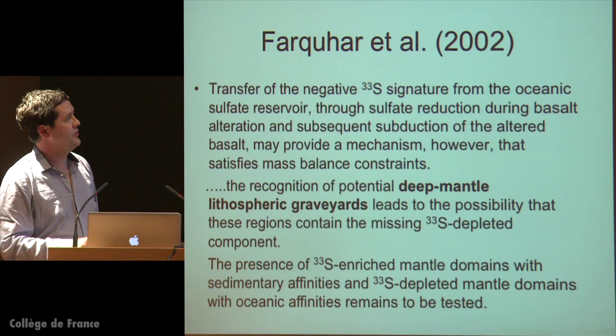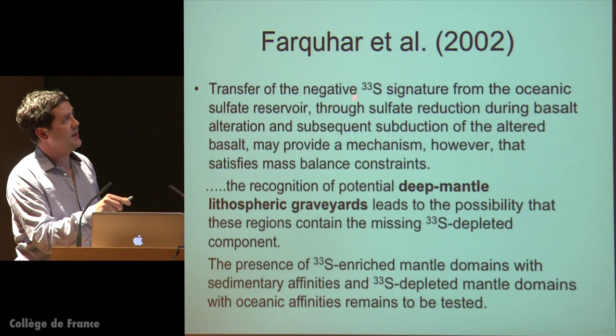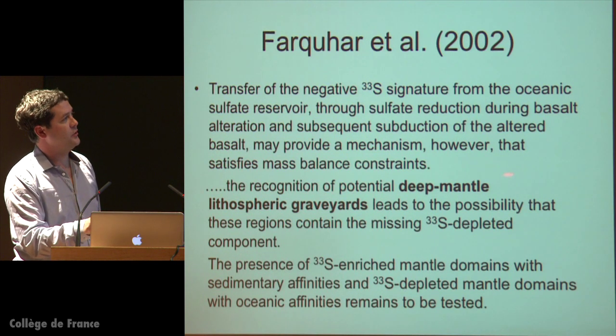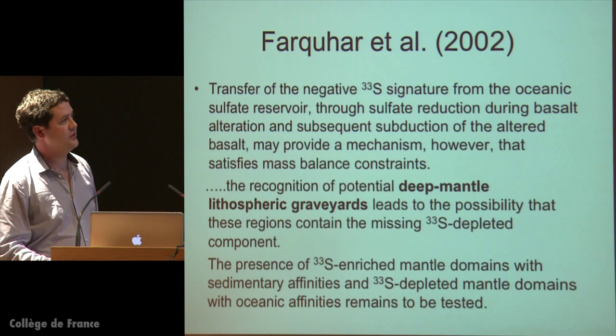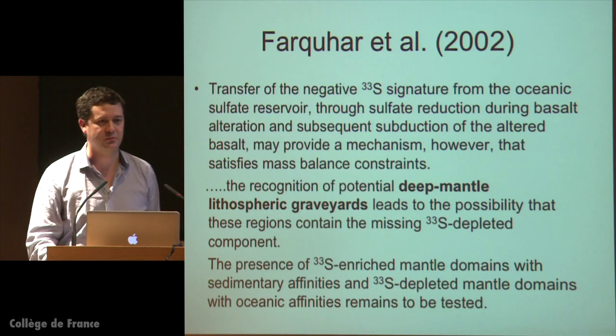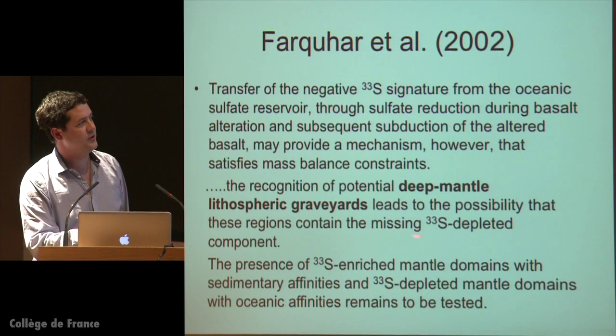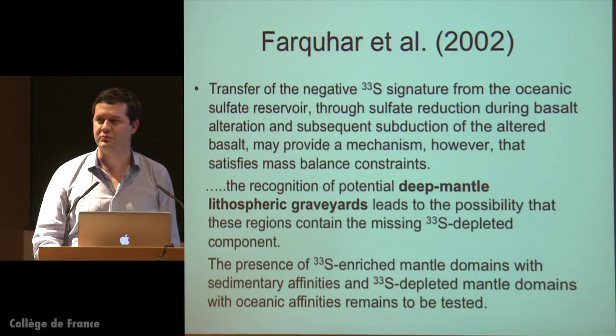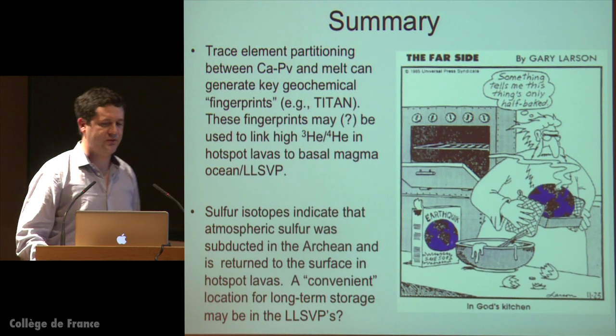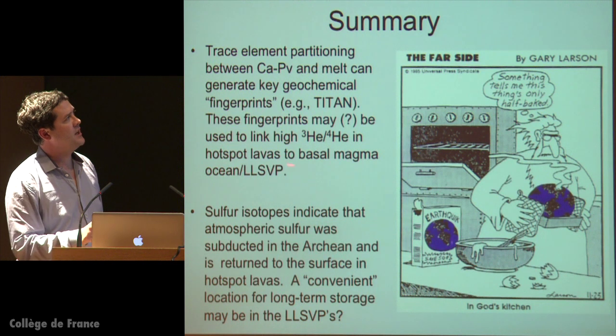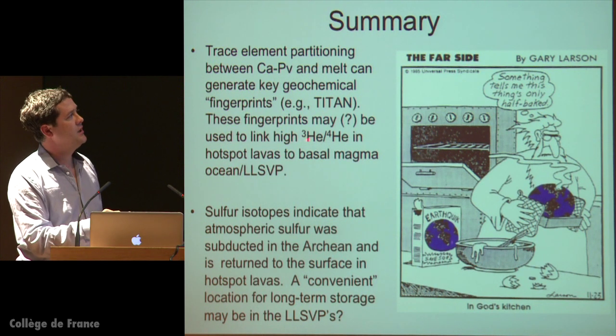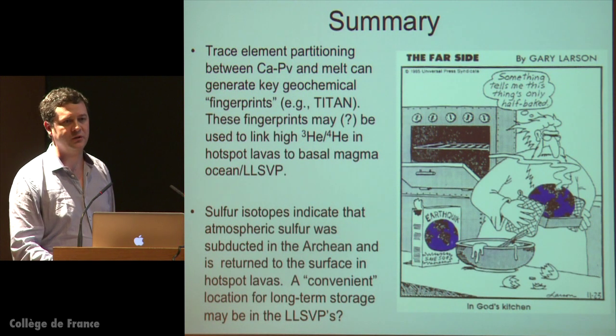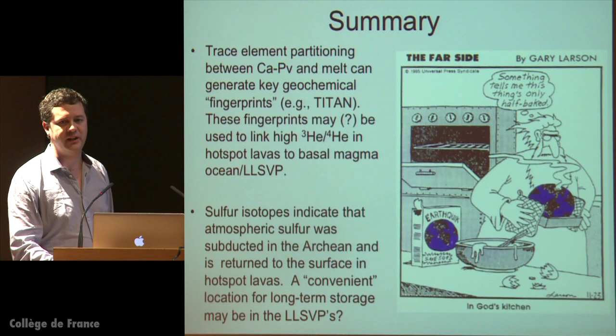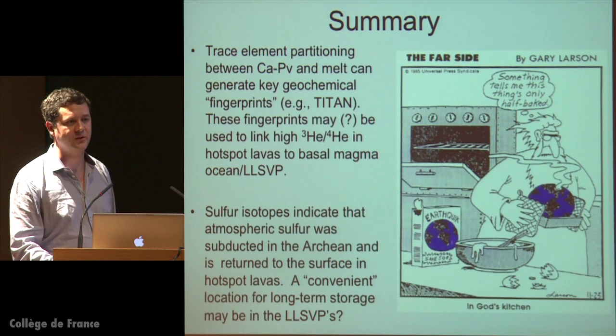And just again, James was amazingly prescient to realize that this negative Δ33S sulfur signature could potentially reside in deep mantle lithospheric graveyards, so that the complement to the positive Δ33S anomaly found in diamonds could reside in these ancient slab piles at the bottom of the mantle. So in summary, I think we might have evidence to tie the high helium 3/4 signature to the deepest mantle where melt would be in equilibrium with calcium perovskite. There are some trace element signatures unique to high helium 3/4 lavas that are really hard to generate, and I think calcium perovskite might be a way to do this.